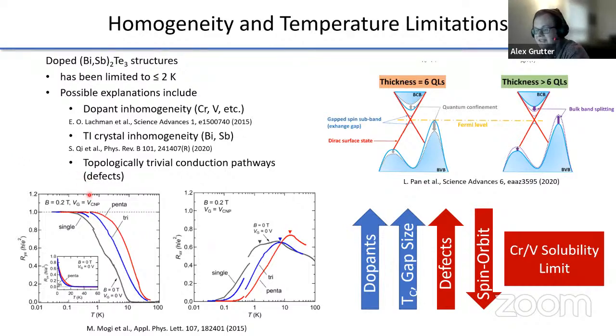So what this means is that basically, as you cool, you don't really achieve a fully quantized quantum anomalous Hall state until usually you're below a few hundred millikelvin. In some really nicely designed modulation doped structures by Mogi et al., they were able to push this up to around 2 Kelvin. But that's about it. And there are a lot of sort of potential explanations for this behavior.